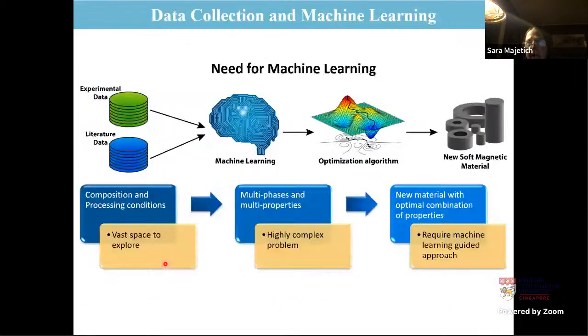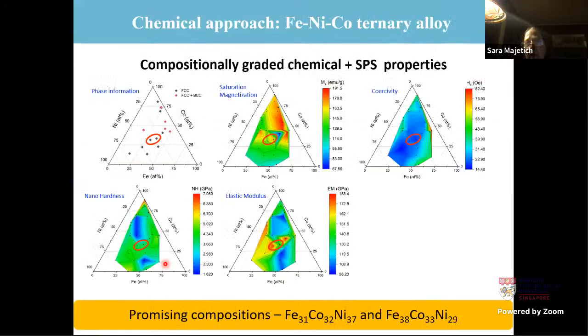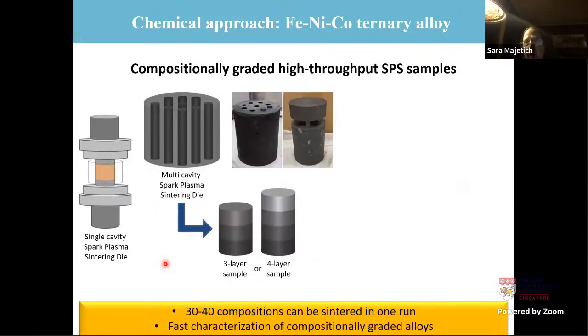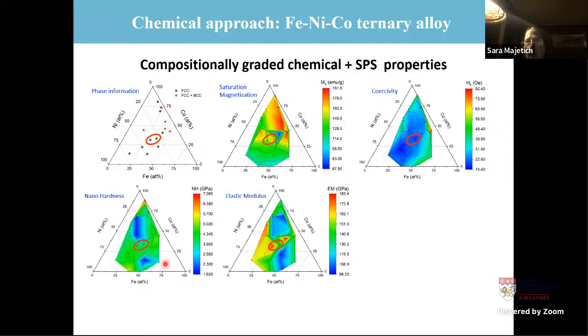Very nice talk, very interesting talk. I'm curious about the generality of this approach. It seems that with iron, nickel, cobalt systems, you're looking at cases where the elements are highly miscible with each other. But you also mentioned aluminum, iron, cobalt, nickel. And I think of alnico magnets, which have really beautiful, complicated microstructure where they get phase separation of different elements. Is your technique going to be applicable in those kinds of cases?